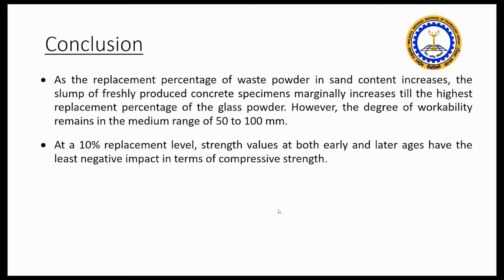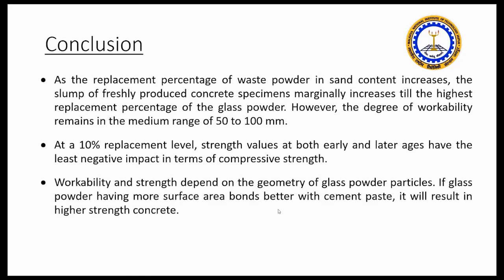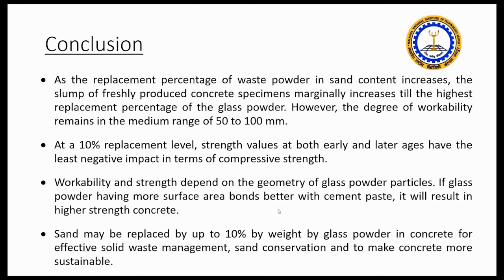At the 10% replacement level, strength values at both early and later stages have the least negative impact in terms of compressive strength, and workability and strength depend on the geometry of the glass powder particles. If the glass powder has more surface area it bonds better with cement paste, resulting in higher strength. So we could use another method of crushing the glass bottles to get a different shape and geometry, from which we can get higher strength too.